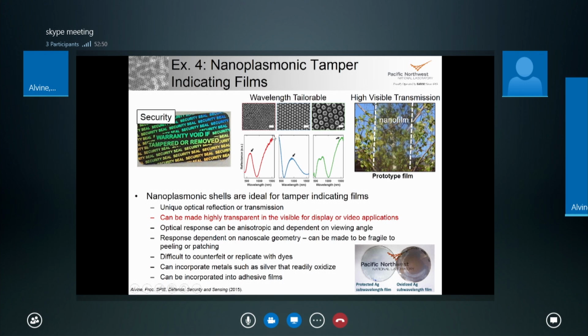Because these have a very unique spectral signature, it's very hard to damage them and still retain those properties without noticing it. Additionally, by incorporating silver, we can get an effect where the plasmon resonance essentially turns off because the silver oxidizes. You can see in this bottom figure, you go from a clear state to a dark brown state when the silver becomes oxidized in these nanoplasmonic films.